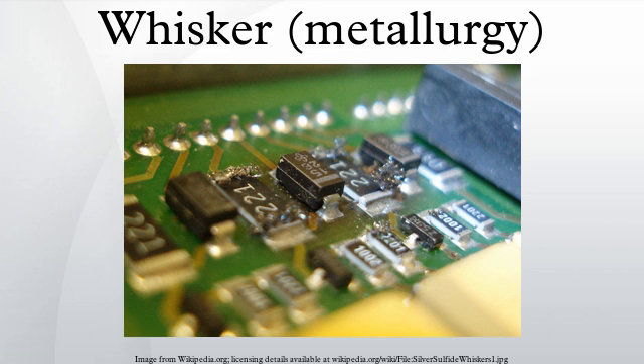Whiskers can form on the underside of zinc electroplated floor tiles on raised floors due to stresses applied when walking over them. And these whiskers can then become airborne within the floor plenum when the tiles are disturbed, usually during maintenance. Whiskers can be small enough to pass through air filters and can settle inside equipment, resulting in short circuits and system failure. Tin whiskers don't have to be airborne to damage equipment, as they are typically already growing in an environment where they can produce short circuits.